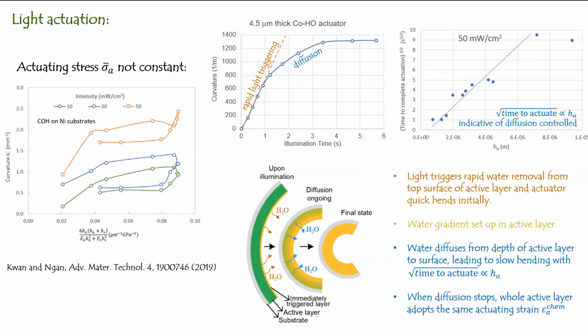But once the surface layer becomes drier, diffusion would occur. So the water from the remainder of the active layer will gradually diffuse out, and then the entire active layer will now shrink as a whole. And that is this slow process. So the light actuation is a lot more complicated than electrochemical actuation, as we have now found out.